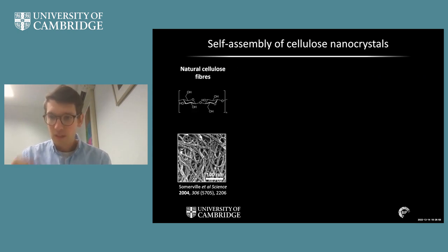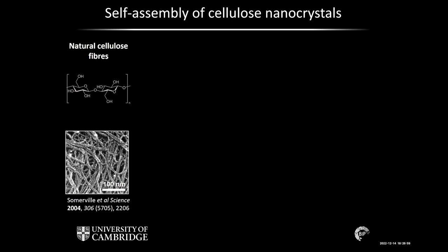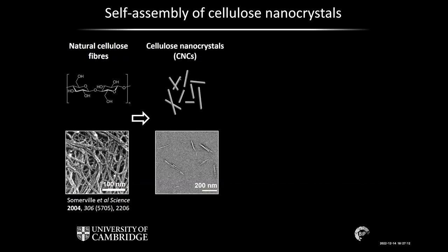And so how do we make these colorful structures? Well, we start from natural cellulose fibers, and then using acid hydrolysis, we essentially break down the bonds along the chain axis for the cellulose, and we can create these cellulose nanocrystals, or what I'll refer to as CNCs, which are essentially pieces or segments of these microfibrils that we cut out of the natural cellulose fibers. And so you can see at the bottom here in this electron microscopy image that they're a couple of 100 nanometers long. They're smaller than we can see by eye, and they're more or less rod-like in shape.